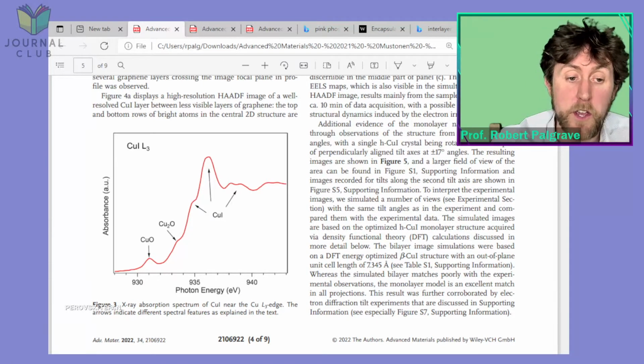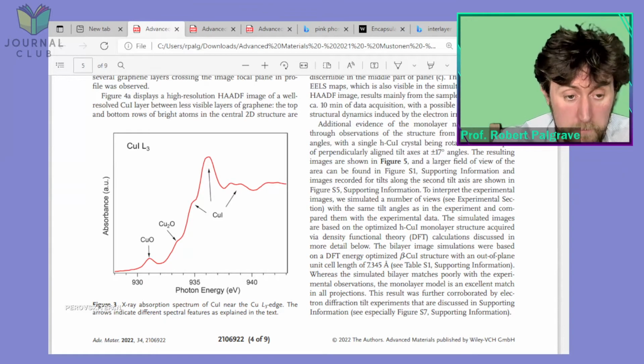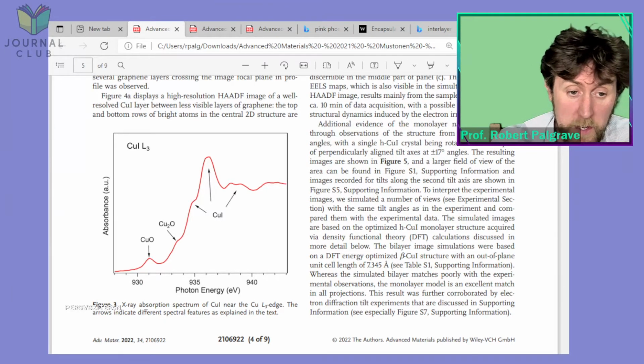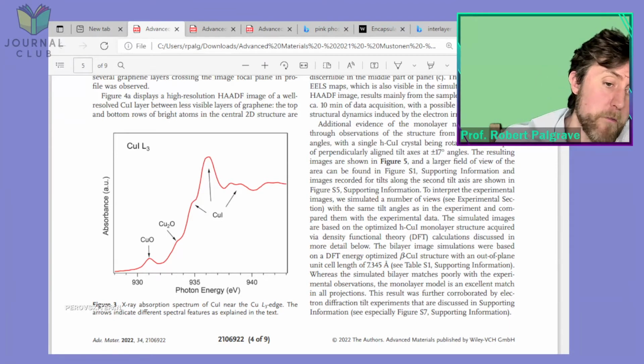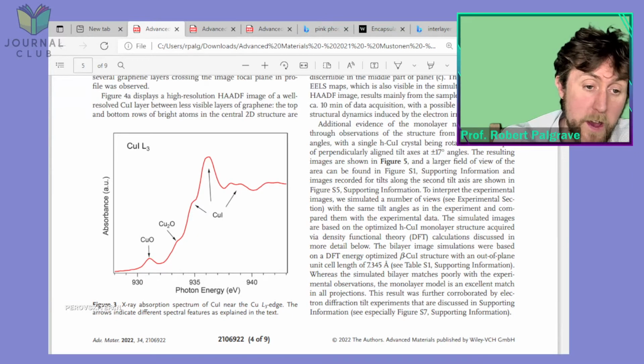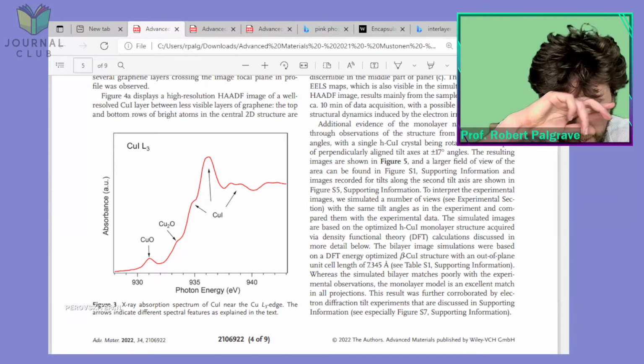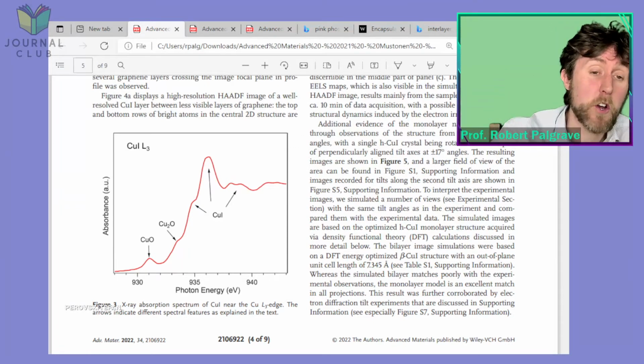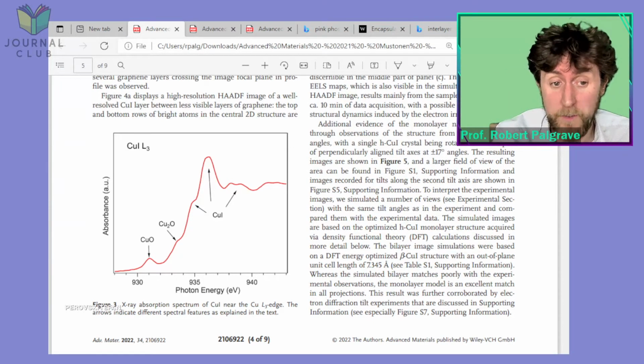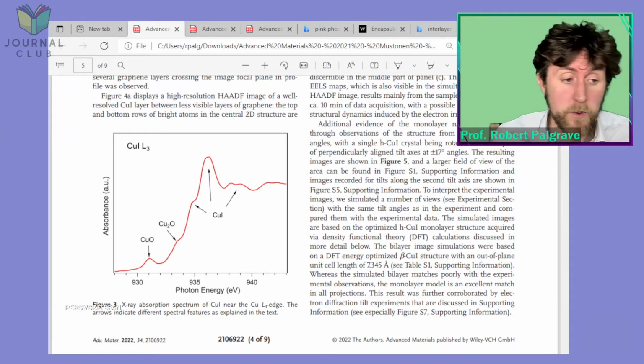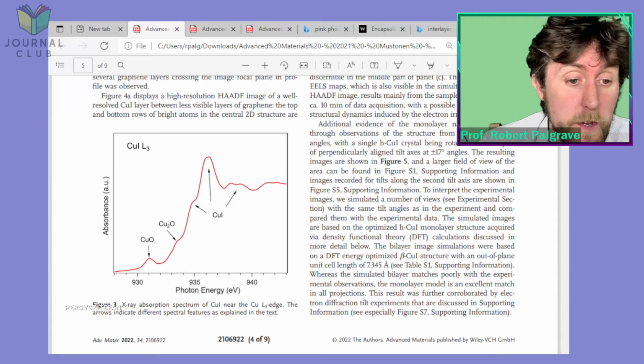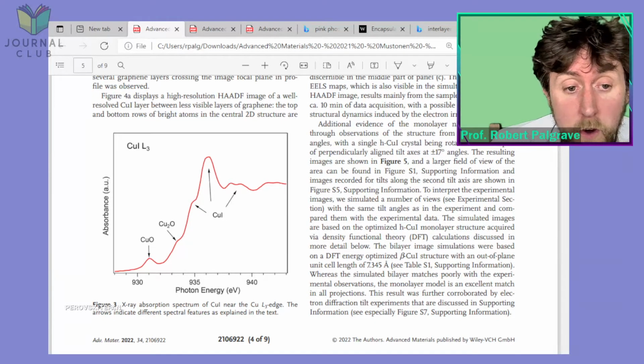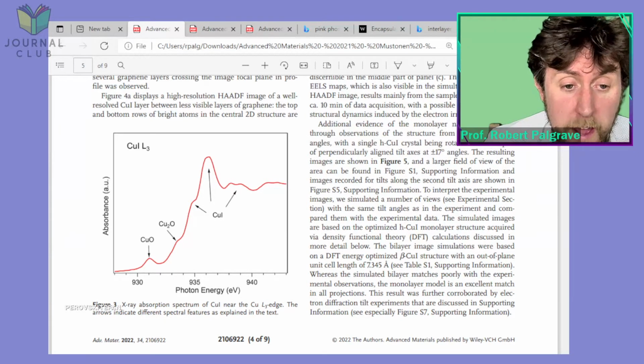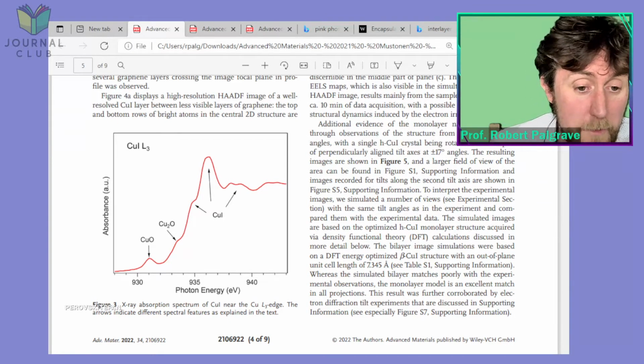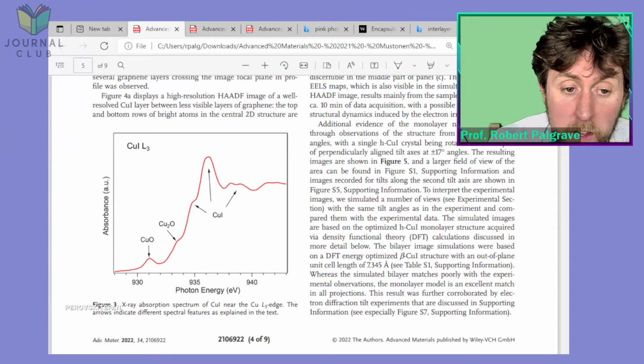So they're saying that copper oxide, CuO, sorry, copper 2 plus oxide, not cuprous, this is cuprous oxide, Cu2O. Copper oxide has a peak here. Cuprous oxide has a peak here. So they're saying they have some oxides of copper here, which is quite interesting. I don't know whether the copper chloride has reacted with the graphene oxide, because remember they had a lot of oxygen in their system from the graphene oxide to start with. Maybe that's where the oxygen comes from in this sample. I don't really know. Copper iodide, cuprous iodide, they're confident that they have these peaks here, which they think correspond to cuprous iodide. I'm not really an XAS expert.